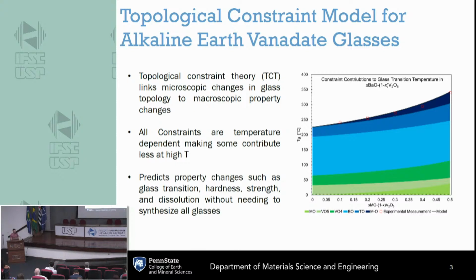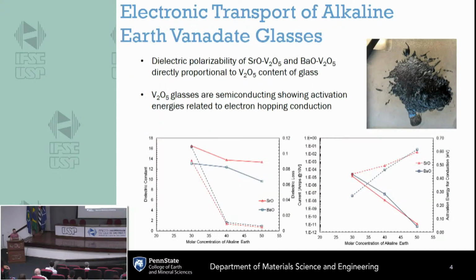So here I show a figure that we can use to predict glass transition temperature as we change the modifier content in these vanadate glasses. And this is also applied to hardness and elastic moduli. Also, I have been studying the electronic transport properties and also dielectric and dielectric loss of these glasses. So in the bottom left, we can see that as strontium oxide and barium oxide are added to these vanadate glasses, the dielectric constant decreases along with the dielectric loss. Essentially, the vanadium oxide concentration is directly proportional to these.